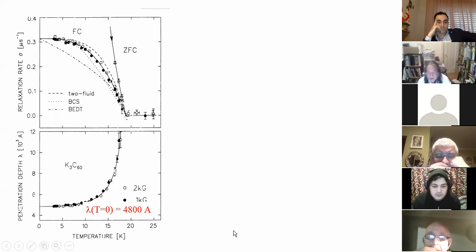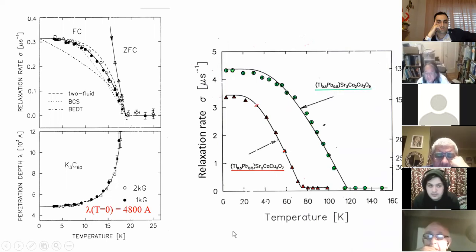measurement we can do in essentially if you have the sample specimen, any of various different superconductors. So I'm showing you here very early data taken in high temperature cuprate superconductor about 2 years after the discovery. And by changing chemical composition, you can make various different high temperature superconductors having different transition temperatures. So this is a result of the material with transition temperature of about 70 Kelvin and 120 Kelvin.